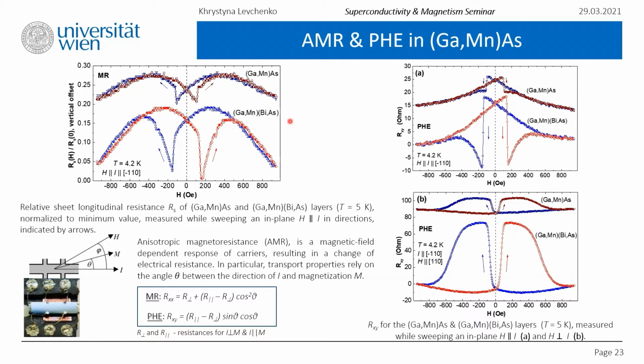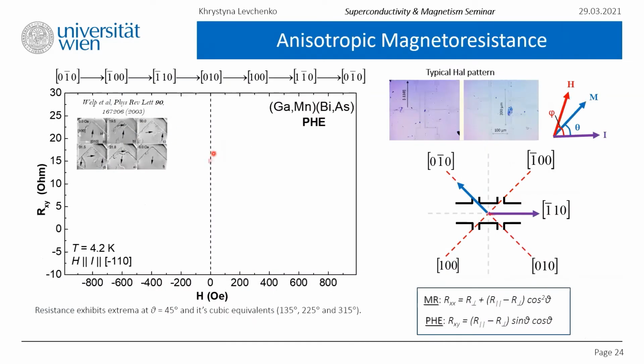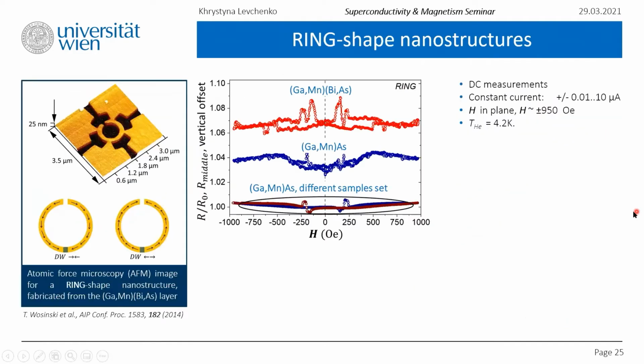For the transport, we see that as well, the same phenomena are governing both ternary and quaternary compounds in low temperature and low fields. But comparing the two curves, we see a distinguishable increase of the magnitude, increase of the coercive field, and increase of the anisotropy field in the case of addition of bismuth. And this will be important for us in just a few seconds. So this all, frankly speaking, was a prelude to be able to play further with these materials.